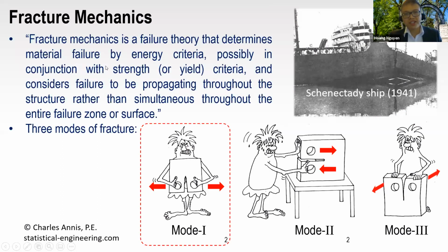So to start with, fracture mechanics started from some unfortunate incidents during World War II, where some ships accidentally failed. However, the design strength still satisfied the requirement, but they still failed, and the strength at which they failed was lower than expected. And then Griffith started a fracture mechanics study and came to the definition of fracture mechanics as a failure theory that determines when and how the material fails based on the energy criteria, not on the strength criteria. And the failure can propagate throughout the structure rather than simultaneously or immediately failing the entire zone or surface.